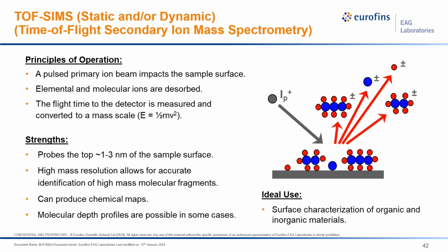Dynamic time-of-flight SIMS operates by, for us, we use a pulsed primary ion source. And as you can see from here, you have the ejection of positive and negative secondary ions. Hopefully we have some intact molecular ions and larger fragments, so we can get the most chemical specificity of these three techniques I'm talking about. Again, Auger, elemental, XPS, we get some chemical bonding, next nearest neighbor information, and with time-of-flight SIMS, hopefully we can get some full organic information about the materials on the surface. Time-of-flight SIMS is the most surface sensitive of the three, with a 1 to 3 nanometer sampling depth.